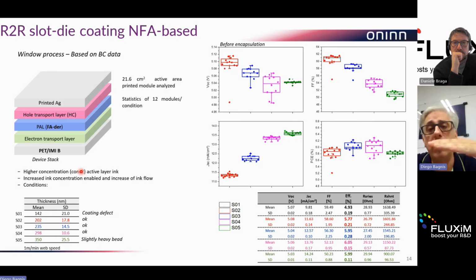Just to remember, in blade coating you have the substrate fixed and the head moving, so the meniscus created is slightly different compared to the slot die, where the web is moving and the head is fixed. And so in that way, it is generally necessary to increase the concentration, and you have some limitation. As I mentioned before, there is a limit at about 200 nanometer of thickness. For example, at 140 nanometer, we see coating defects. And just to show, here in the table, you see that we have lower results. Here in the graph it is not mentioned.